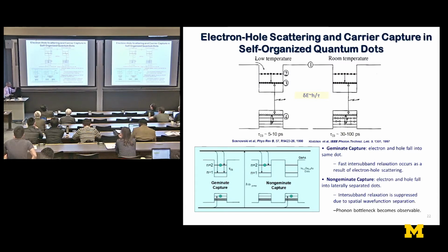And this was something very fundamental, that in quantum dots, the main scattering mechanism that relaxes energetic or hot carriers is this electron hole mechanism. A hot electron scatters with a cold ground state hole, gives its energy to the hole, and the hole, of course, comes higher in energy, and then it relaxes by multiphonon emission. And that's how the electron quickly comes down. But as you raise the temperature, the holes thermalize, and there are not enough cold holes for the hot electrons to scatter with, and the process slows down, and that's what slows down the laser modulation and everything else.